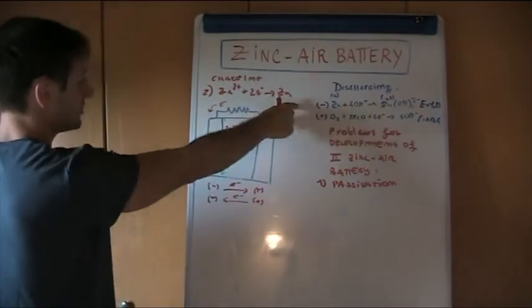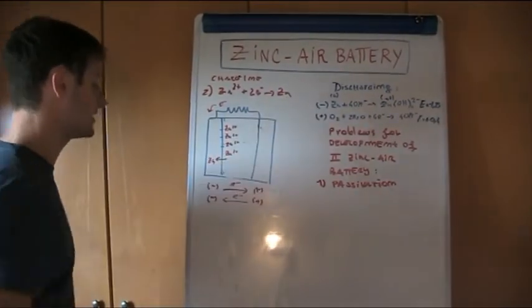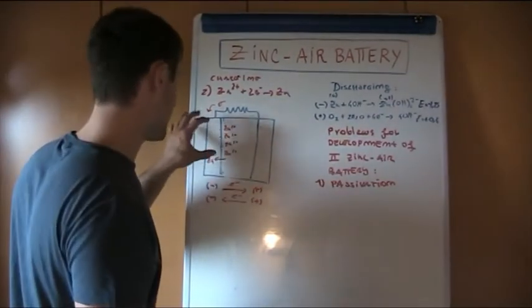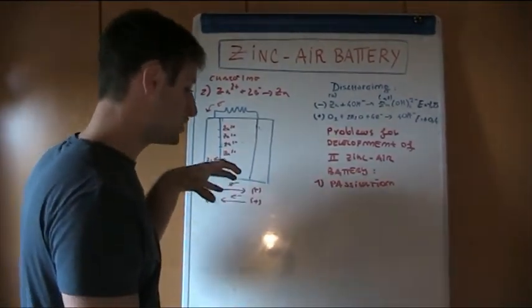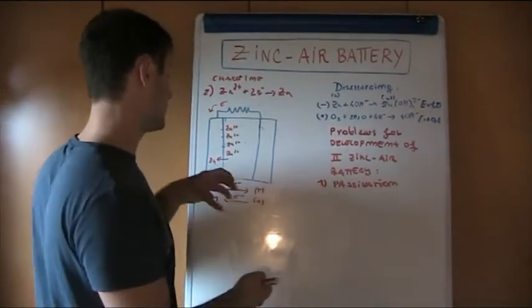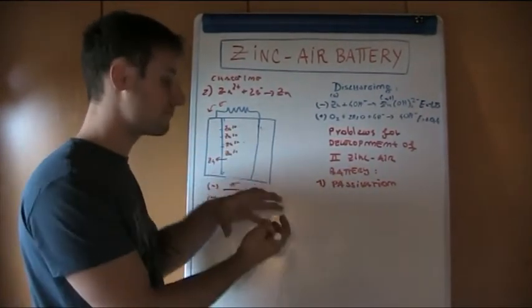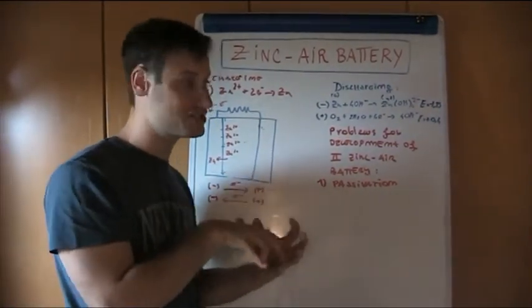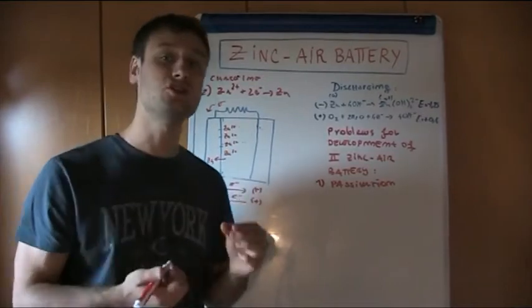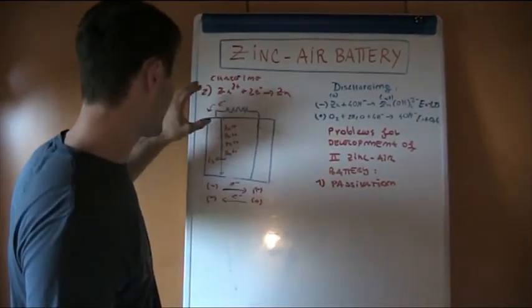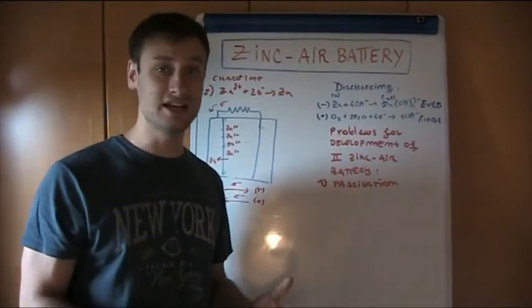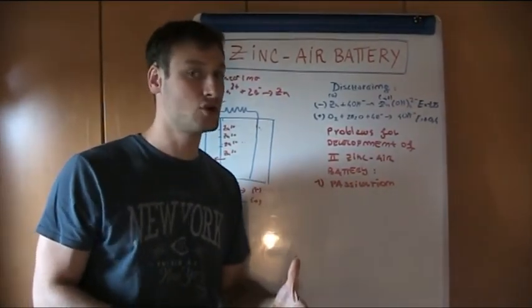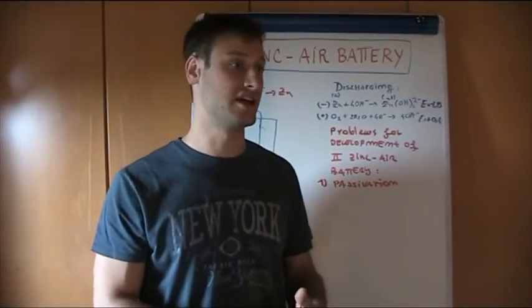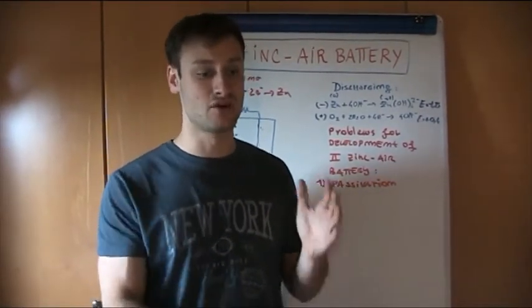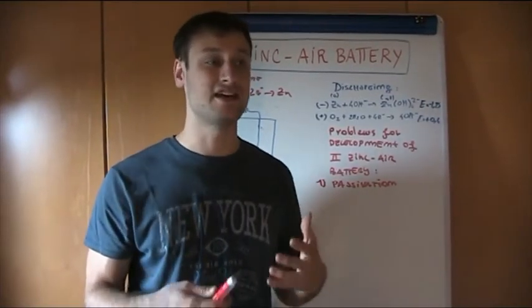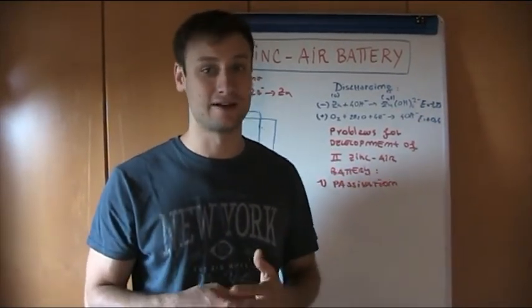When we are forcing the reduction in order to recreate metallic zinc, the problem is that since we have a huge amount, we can generate aggregate. So basically these types of zinc 2+ can react in sort of blocks of metallic zinc. And in general, the redeposition is not uniform, because at the very beginning we have a very uniform zinc electrode, because we have designed it in the industry, basically in a company with specific machines in order to homogenize the surface, and it is basically created in a form.